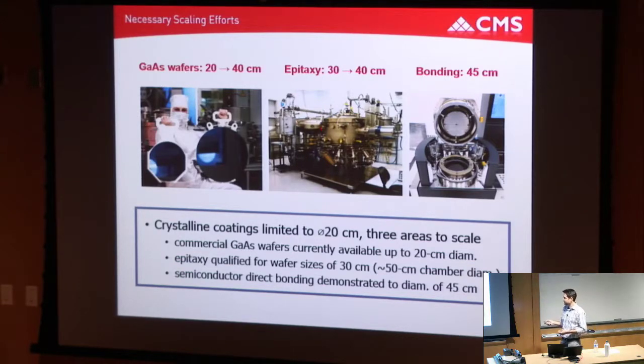There are epitaxial growth systems. These production chambers are 50 to 60 centimeters in diameter. The uniformity looks good enough, if that wafer could be produced and popped into the machine, that you could grow it at high enough uniformity. And then you need to modify the bonding systems. There are currently silicon on insulator wafers, so these are silicon oxide silicon stacks made by bonding, up to 18 inches or 45 centimeters in diameter. But again, they accept wafers. They're made for standard semiconductor wafers, not a test mass that's 20 centimeters in thickness, so that has to be modified. But the pieces are in place to do it. It's just very capital equipment intensive. That's the biggest roadblock here.